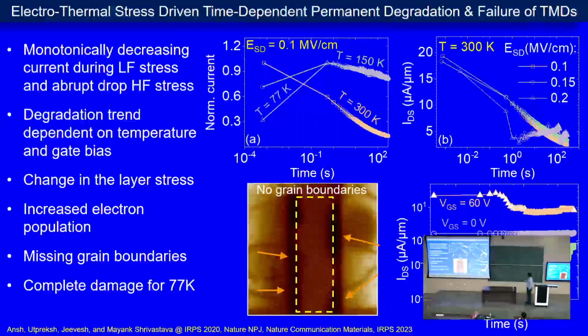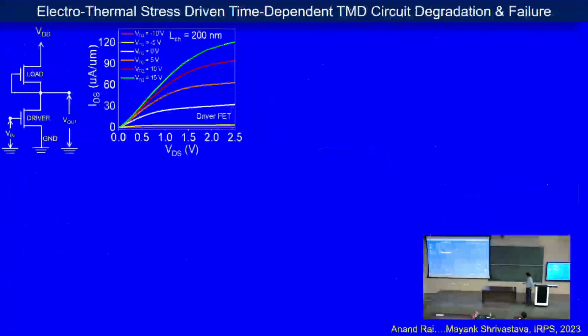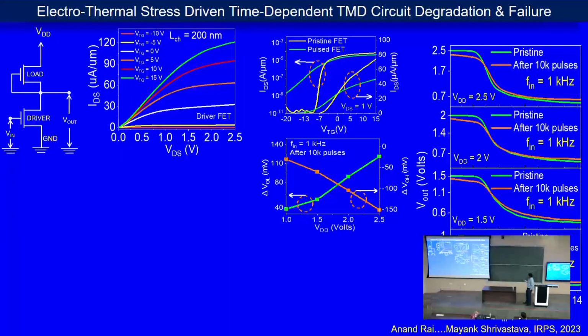This was another work where we demonstrated for the first time, which came in Nature, that the TMDs, if you stress them, you just apply a field, the material is going to change its phase as a function of time. So this time dependent channel degradation or phase change of the channel was reported for the first time, and we found there's a particular critical field with a strong function of the temperature, the electrostatic state of the channel, and many other things. In fact, this year in IRPS we published circuit reliability work. So we also demonstrated circuits based on 2D materials, and then we demonstrated how the circuits will degrade as a function of stress and time.